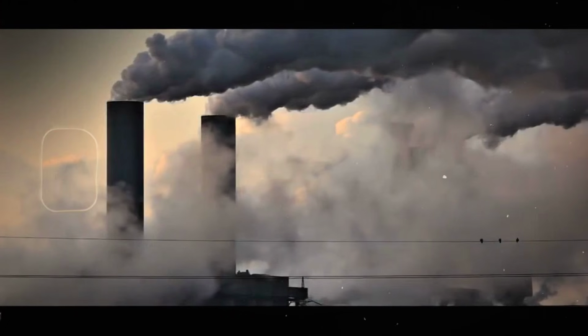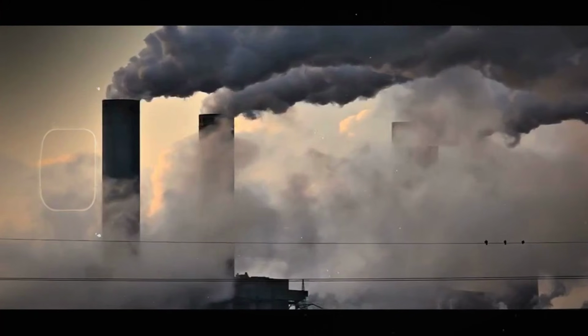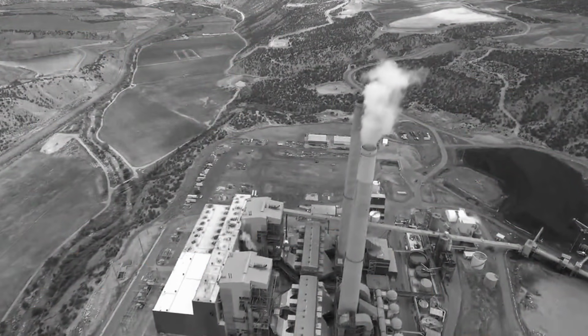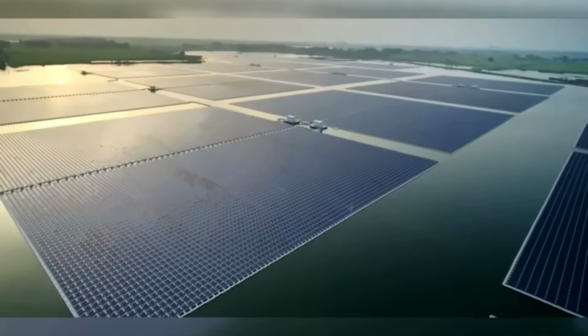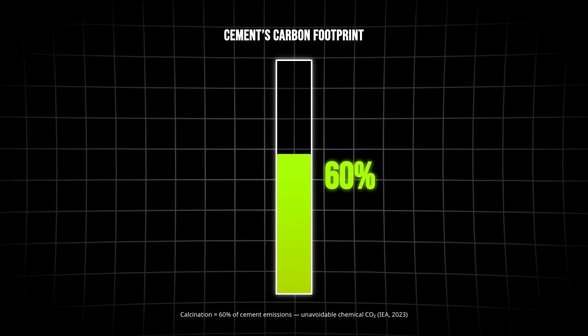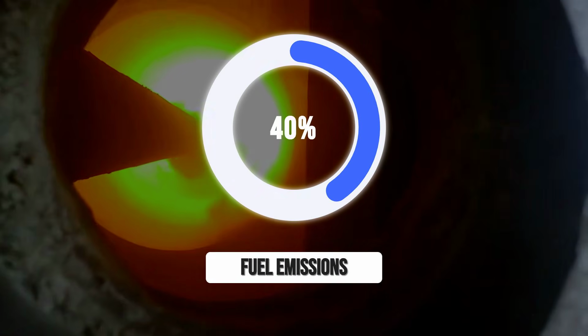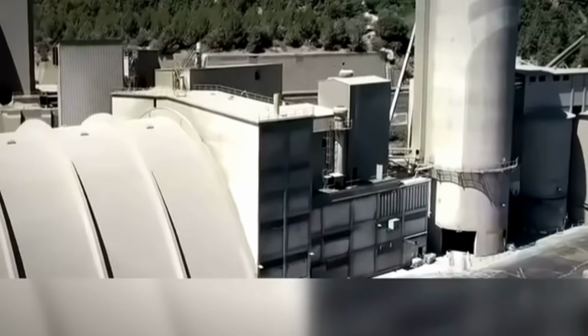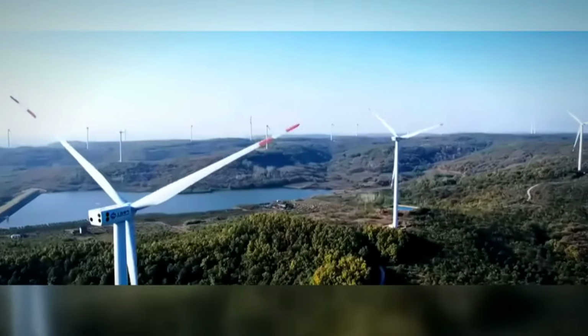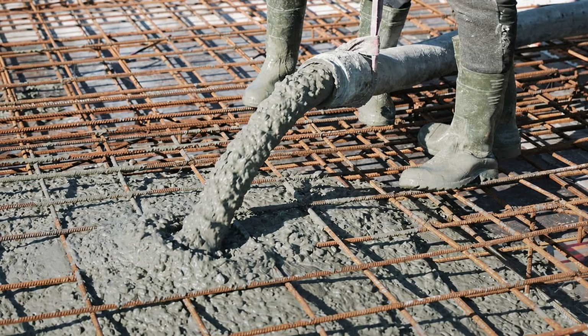The carbon dioxide it releases is not combustion waste. It is not the exhaust of a dirty power source that could be replaced with a renewable one. It is a direct molecular output of the chemical transformation that makes cement possible. Approximately 60% of cement's total carbon emissions come from calcination alone, regardless of what fuel powers the kiln or how efficiently the facility operates. The remaining 40% comes from burning fossil fuels to reach the required temperature, a portion that cleaner energy can theoretically address. The 60% cannot be addressed by an energy transition at all.